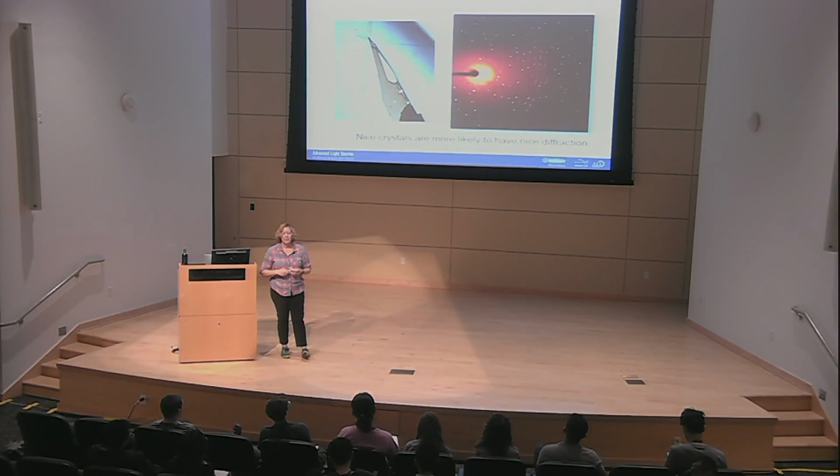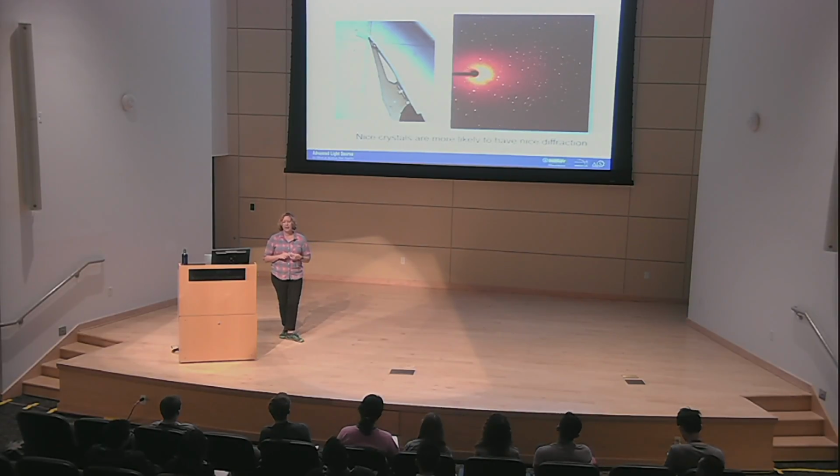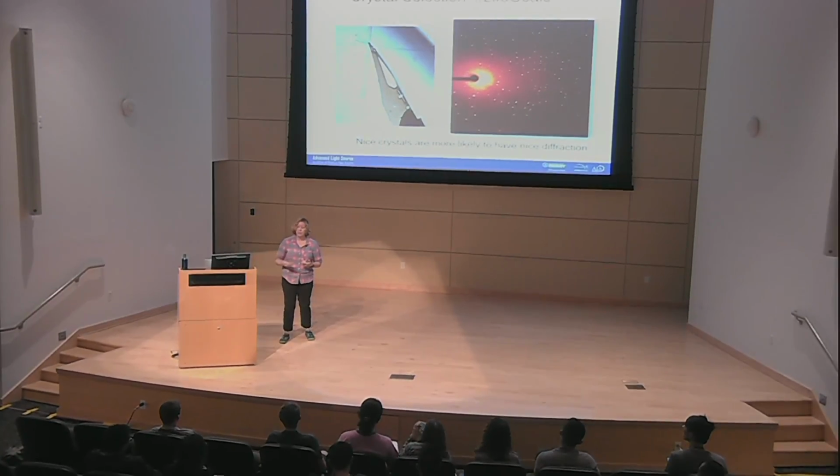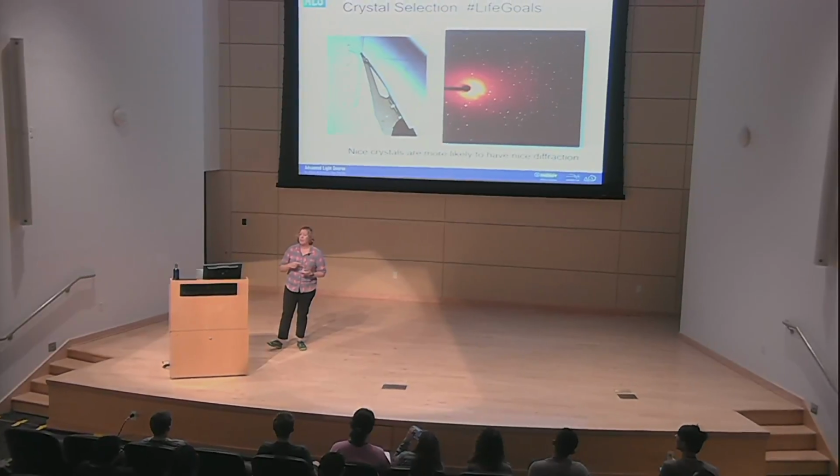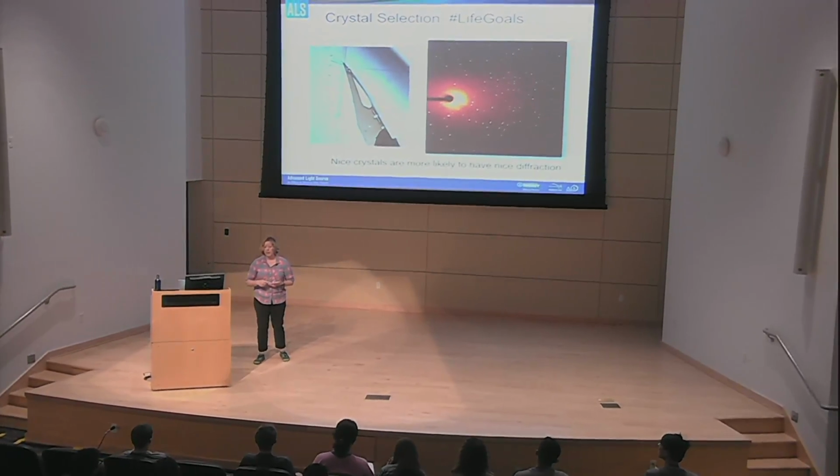How about the chiral nonsense? So if you're looking at chiral twins, usually you're looking at the Flack parameter. If you have chirality present in your system, then you know that you cannot have space groups that have mirrors if you're enantiopure. So if you have an enantiopure compound, then your space group should not have any mirrors or inversion centers.